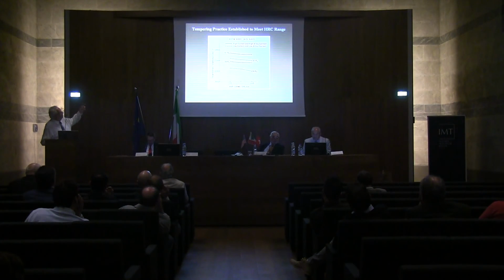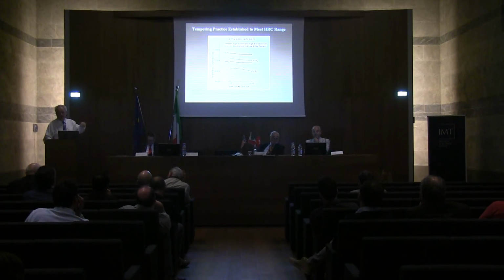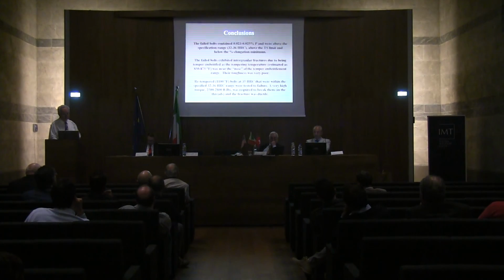And the solid line is high carbon, high alloy content, because there's a composition range to 4140. You know, there's a certain range of carbon, chrome, manganese, and everything. And so I calculated the hardness as a function of bar diameter and tempering temperature based upon the top of the limit and the bottom of the limit, for getting 32 or 36 Rockwell C. So we could have really good data to decide what tempering temperature to use.